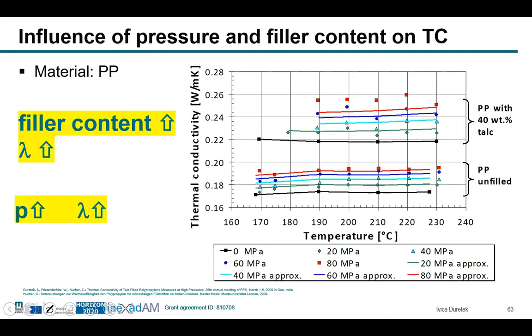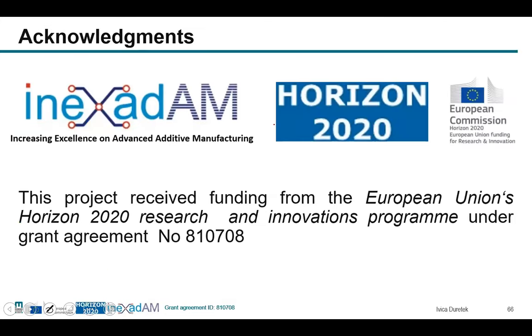In this slide are the results of the measurement on the same material. And we can see additionally the influence not only of the pressure, but also of the fillers. 40% of talc increases the thermal conductivity by approximately 30%. And this is all of my slides.